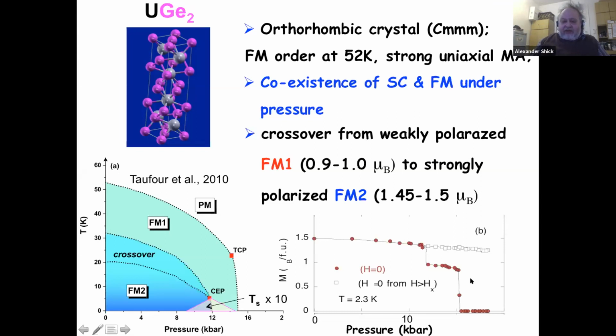If you don't apply the field, this phase actually has a low moment, around 1 Bohr magneton. Then you cool it down and you cross into what is called the FM2 phase, which has a higher moment, about 50% higher. Then once you apply pressure, you end up in this superconducting dome, which eventually corresponds to this critical point where the FM1 meets the FM2.